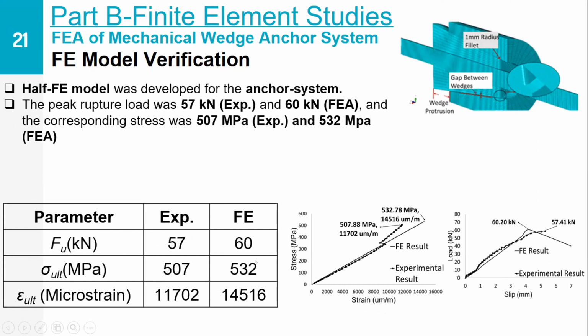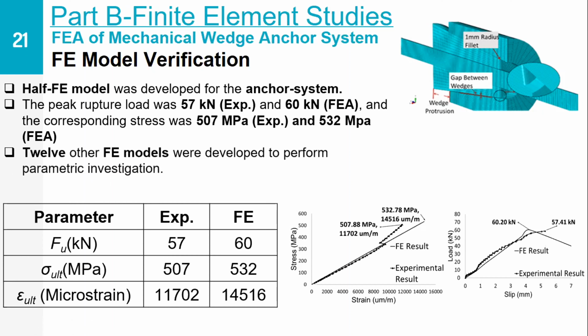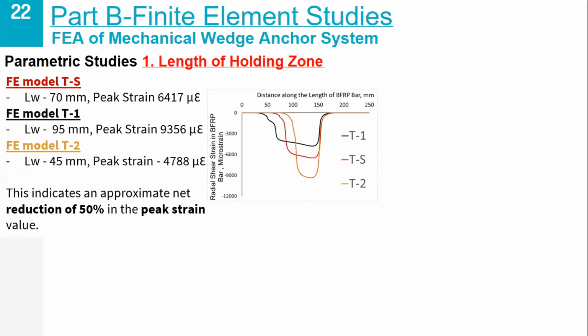And the ultimate stress was also quite close to the stress that has been obtained from the experimental results. However, this ultimate strain was slightly higher. However, you can see from this load-slip relationship as well as the stress-strain relationship, they are quite close, and hence this model has been further used to conduct parametric studies for 12 other FE models that has been developed to study various parameters. So some of the first parameter that has been investigated is the length of the holding zone.